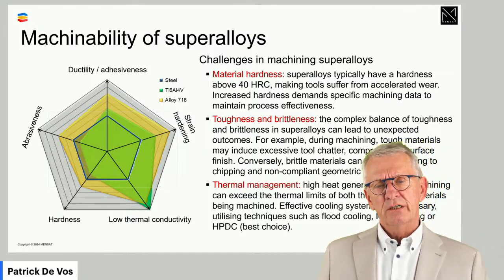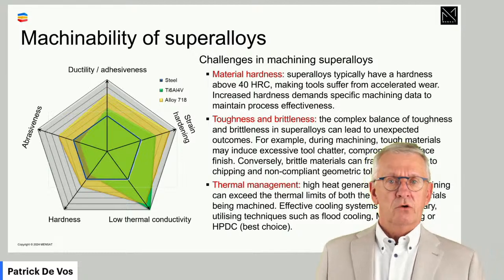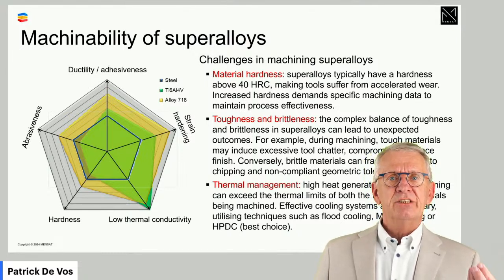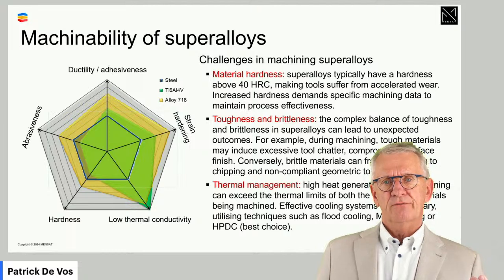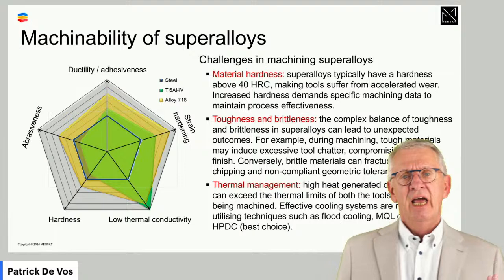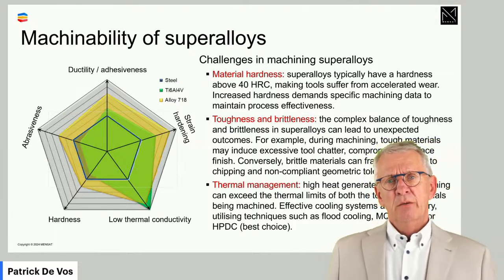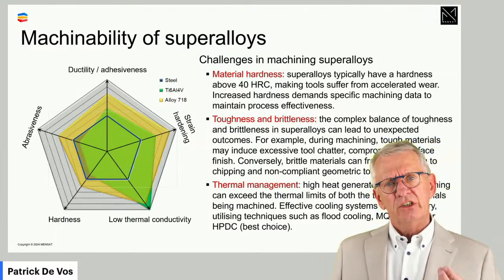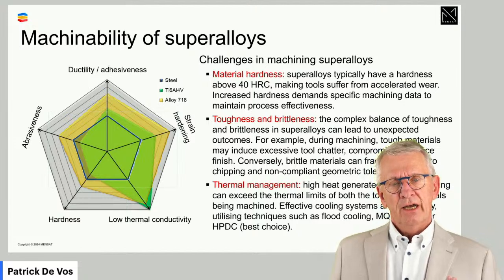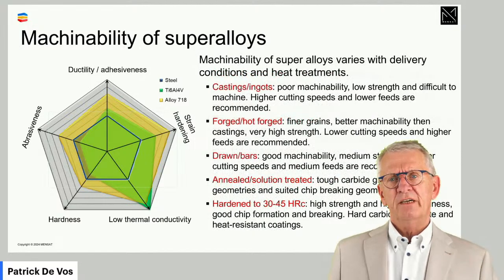So if we have to machine a superalloy or a titanium alloy, it's strain hardening we will have to cope with much more than what we are used to when we machine steel, and low thermal conductivity. But if you look to the yellow and the green part, you see differences. Titanium or a titanium alloy is not the same as a superalloy. There are differences. Also, very careful, much more than in steel.